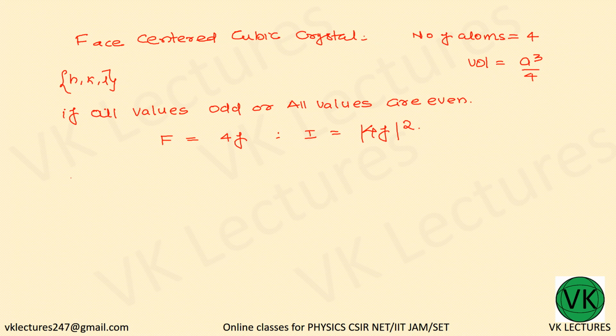Else we have another condition, that if the hkl values are mixed, then F is equal to 0. That means the geometrical structure factor is 0.